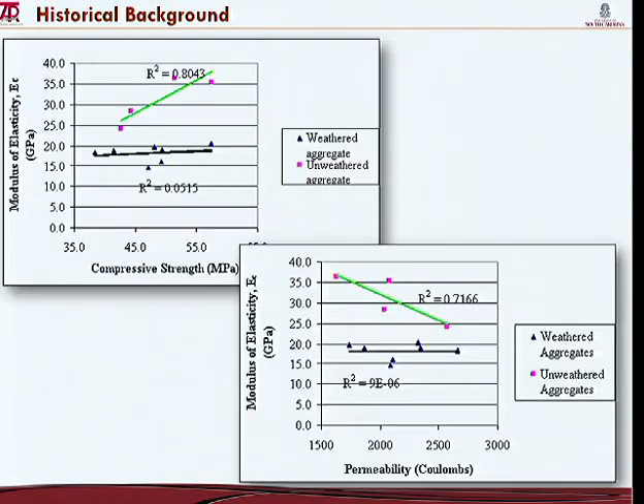Some graphs from this old study, early 2000s, about 10, 15 years ago. This top graph shows the correlation of the modulus of elasticity with compressive strength, and two groups of data. This group is what we call unweathered aggregate, or the standard aggregate that is used. These are granites, and this data here had to do with those batches that did not produce the modulus of elasticity that was expected, and we found out that all these aggregate sources came from quarries where the granite was weathered.